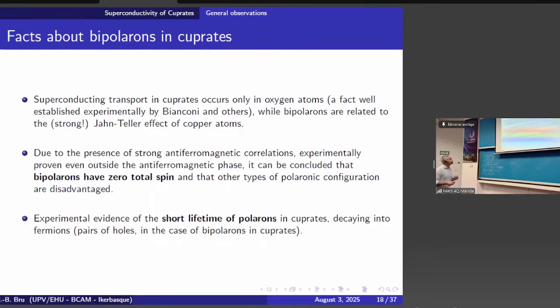Okay, so as I said, the holes only appear in oxygen. Bipolarons are related to the strong Jahn-Teller effect of the copper atom. The bipolarons have zero total spin because it's antiferromagnetic, so it doesn't want to have two holes or two fermions which are spin up. They always want antiferromagnetic correlation, so up and down.